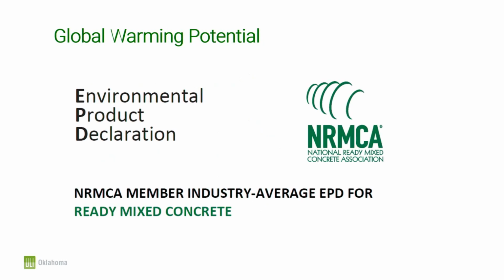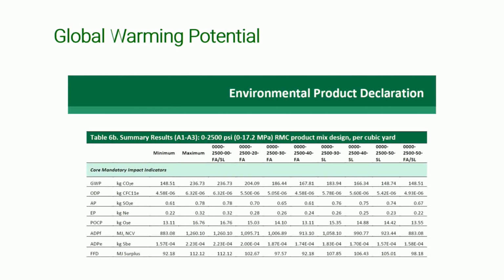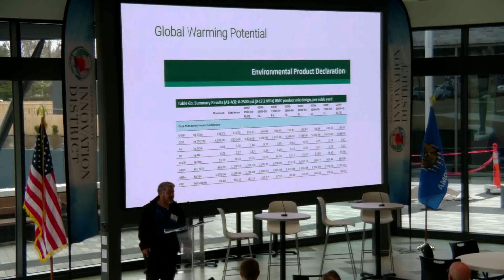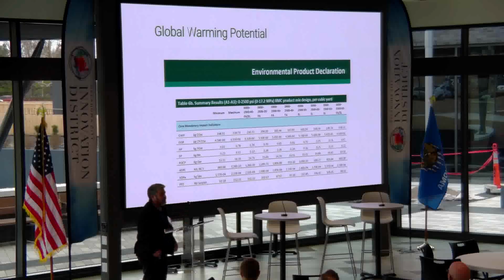I'm getting all these EPDs from what the National Ready Mixed Concrete Association has been producing for a while with their Environmental Product Declaration benchmarks. What NRMCA does is get together a bunch of producers, we send them our normal mixes, and they do the calculation on the global warming potential for each combination of straight cement, cement with 20% fly ash, cement with 30% fly ash, 40% fly ash, slag, and a combination of fly ash and slag. So you can see how the GWP decreases from the maximum all the way down to almost two-thirds or less of what we would have had if we were 100% Portland cement.